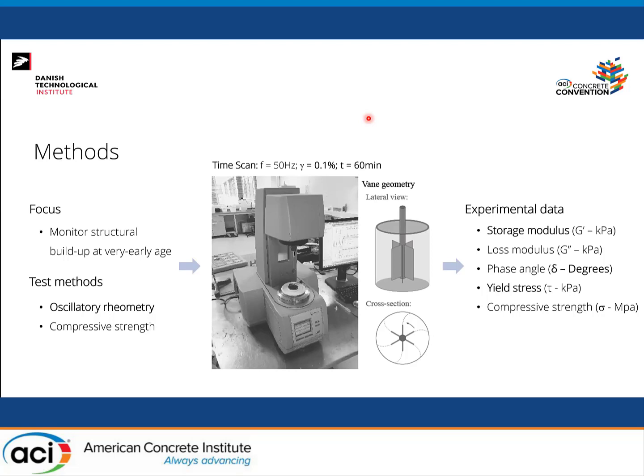And in a more pragmatic way, you could also deduce the value or the evolution of yield stress using penetration tests, which is a much cheaper and much easier tool to use, but then you only have isolated measurements. The advantage of oscillatory rheometry here is that we can map the evolution of important rheological properties over time. And the compressive strength test was the standardized compressive strength test for mortar samples.